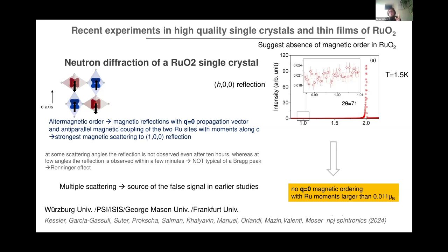So in fact, these ruthenium dioxide crystals are, I think, a millimeter large, and they are quite pure, so quite pristine. And what I'm showing here is the intensity of this reflection that I was mentioning to you. As I was mentioning, you would expect the strongest magnetic scattering along this reflection if we have this configuration. What the neutron scattering measurements show is that there are some scattering angles where, even with observations that have the statistical average of a long time, so 10 hours, they don't see any changes. They don't see any effect at this reflection.